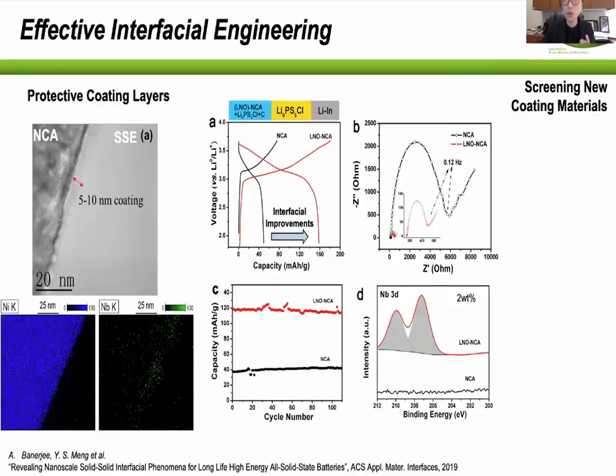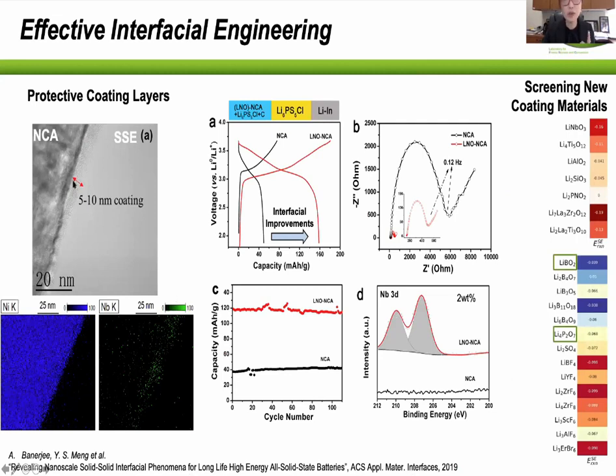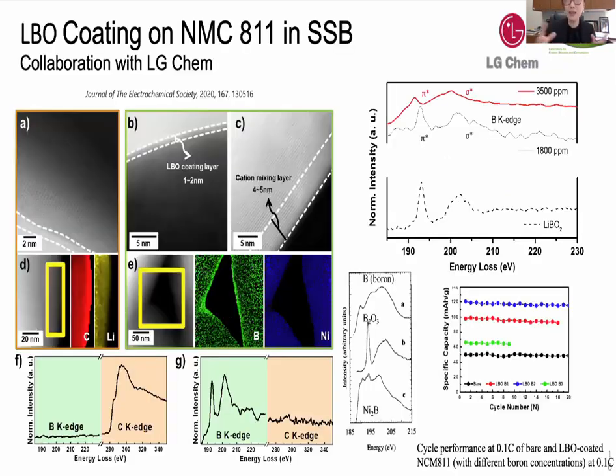So this gives you a huge amount of engineering challenge, because yes, coating has to be applied. And there are lots of coating materials. Lithium niobate is not the only one. You can do phosphates, you can do borates, you can coat the cathode with the solid electrolyte. But just think about the price that comes with those coating processes, right? I think we did this boron coating. Boron is really quite a good light coating material.